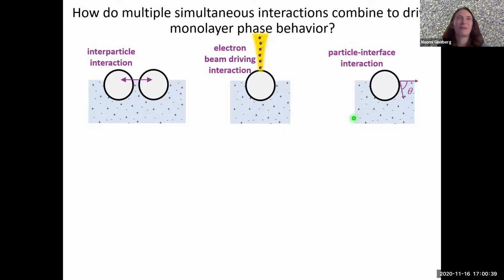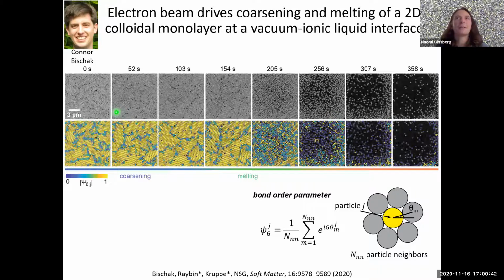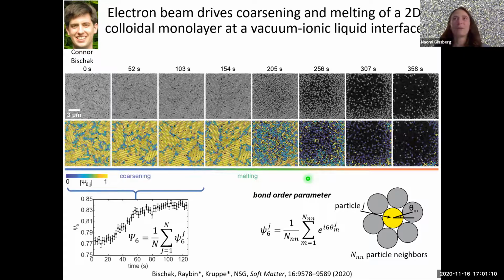Okay, so color coding this same data set by the magnitude of the bond order parameter, a general metric for local hexagonal symmetry, illustrates to us that there are 2 different stages. So coarsening, where the amount of yellow or high value of the bond order parameter is increasing, and then melting, where the yellow completely disappears. There's no time to show you the phase of the order parameter today, but it's also very cool. We've also put a lot of effort into looking at coarsening in that way, but today I'm instead going to focus on melting.